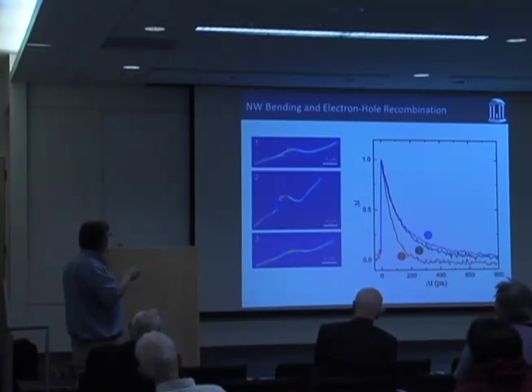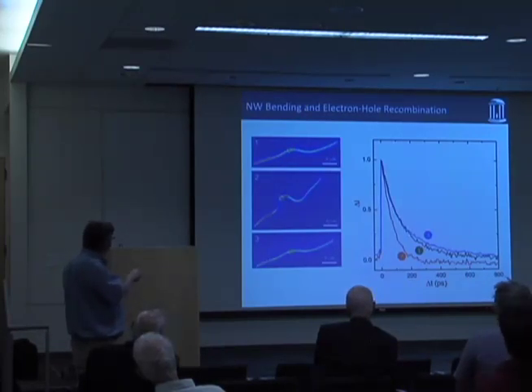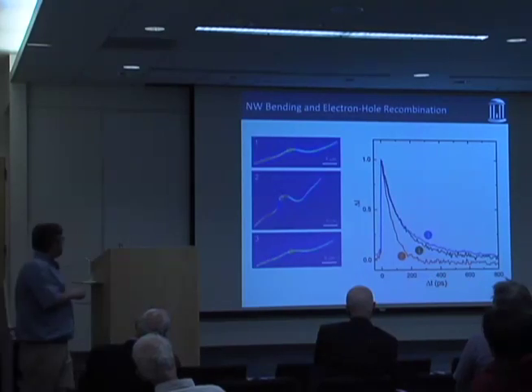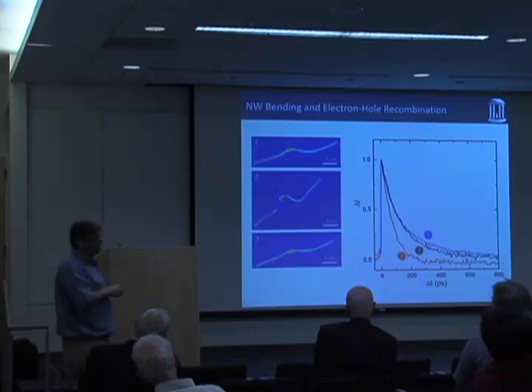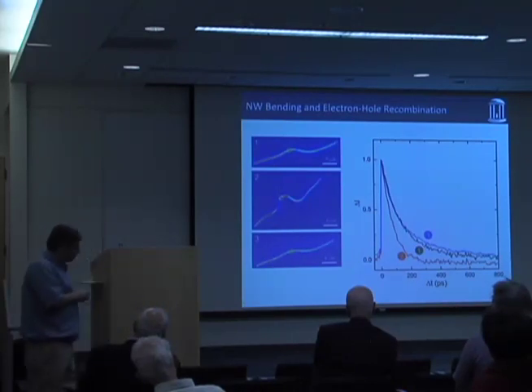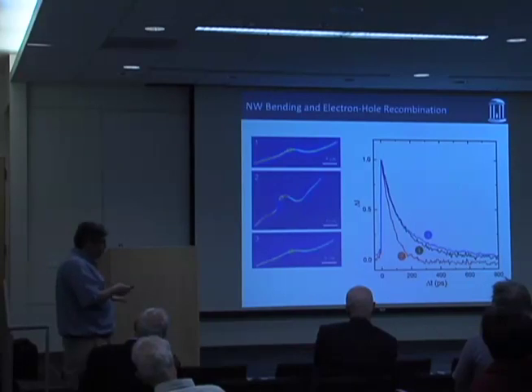And so here's the wire before we did anything to it, and we measured the kinetics here, and that's this black curve. Then you squish it up, and it gets all bendy. And that's the second one, so it gets faster. And then sure enough, as you pull it apart, the recombination recovers and goes slow again. So it really looks like it's a reversible process. And it says probably what we're seeing is we're affecting the band structure of the nanowire and not introducing more defects into the nanowire. All right,